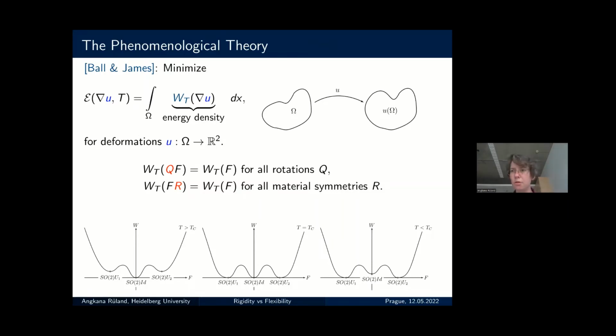So we will adopt a variational continuum mechanical perspective on mesoscopic scales, and assume that our material is originally in the high temperature phase given through some reference domain omega, and that its current state, its deformation, is described by a vector valued mapping U, mapping our domain R2 into R2, describing the current state. Then we will adopt a variational perspective following Ball and James, and presume that the material favors states of minimal energy, where energy in the simplest setting is just a function of the deformation gradient and temperature, the physics being captured in the stored energy density, which should reflect the atomistic picture we'd seen earlier.